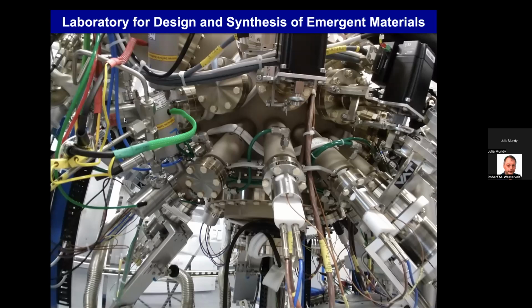And so that was a really cool discovery. That was the first slide I showed, a lot of fundamental physics, but then we got talking to Intel about how you could make a memory device out of this. The idea would be that you could flip the ferroelectric polarization with a voltage, but then it would flip the magnetization. So you could store memory in the north pole, south pole of a magnet, but control it through this voltage. That was a really cool property and a new material. You can't buy it, it's not in the Intel chips or something like that. I don't want to sell it like that, but it really can have very direct connections, even over the time scale of one PhD.